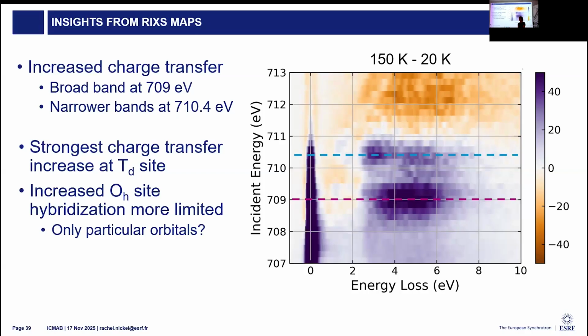Very nice talk. These are the results from nanoparticles. Martí also has thin films. Have you already worked with this, and are there differences between these nanoparticles and the thin films? There's a little bit of a difference. Some of it, it's hard to tell whether or not it's due to geometry effects. Because if we have a powder, we're looking at a powder average. In a thin film, we can orient and we have the opportunity to do some sort of momentum space mapping. We see subtle differences, which modeling-wise, we can attribute to geometric effects.